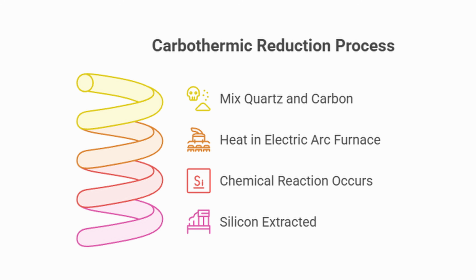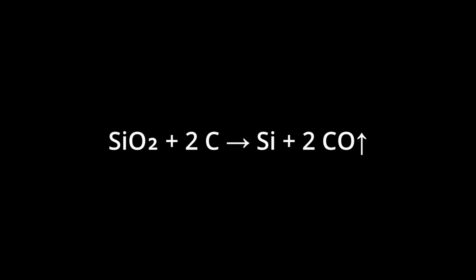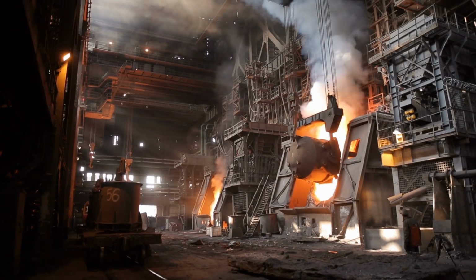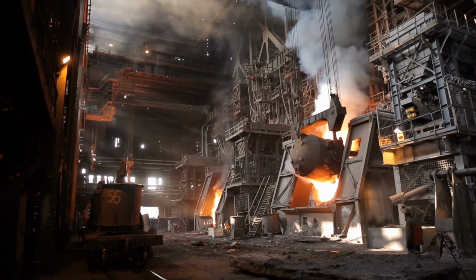At such temperatures, a chemical reaction occurs. The silicon in silicon dioxide is reduced as the oxygen combines with carbon to form carbon monoxide and some carbon dioxide. In simplified form, the reaction is this. Now, the carbon essentially steals the oxygen, leaving behind molten silicon. This process is called carbothermic reduction. The molten silicon collected from the furnace is about 96 to 99% pure. It's often called metallurgical grade silicon.